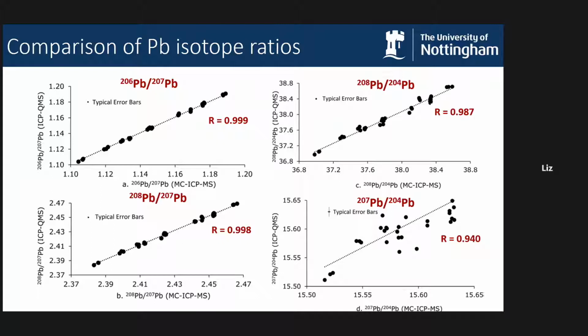And we see this again with the lead 207-204 ratio on the graph in the bottom right-hand corner. Lead 207 is the second least abundant isotope at about 22%. So both of those produce poorer counting statistics, and therefore the ratios that you get for 207-204 are the worst ones that we observe.